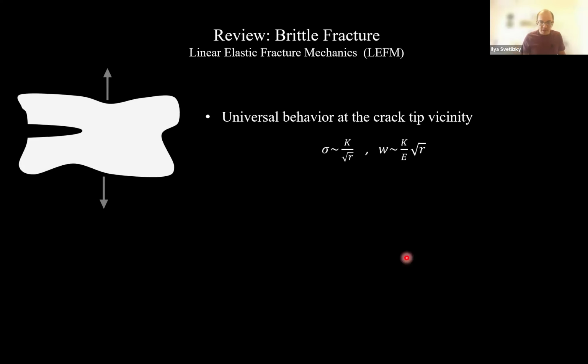So again, I apologize, I will touch base quickly on the basics of brittle fracture theory. Imagine you take an infinite medium. You have a crack, you apply some tractions, and what is amazing about linear elastic fracture mechanics is that it predicts a universal behavior around the crack tip. The stresses diverge like 1 over the square root of R, where R is the radial distance from the crack tip.